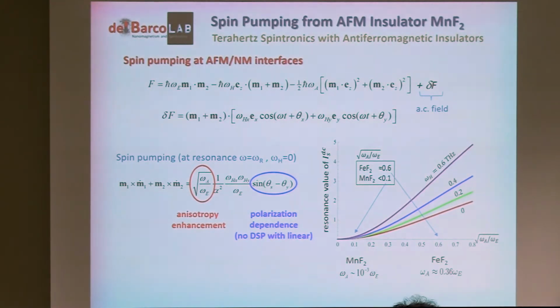So first of all, with an antiferromagnet, you will have much larger spin pumping, much larger spin currents injected into the adjacent metal than with ferromagnets. And the other thing that you can see from here, and this is resolved for zero field, is that the spin pumping will actually depend on the polarization of the light. So you will have to hit your antiferromagnet with circularly polarized light, because if you do this with linear polarization, you won't get any spin pumping, right?